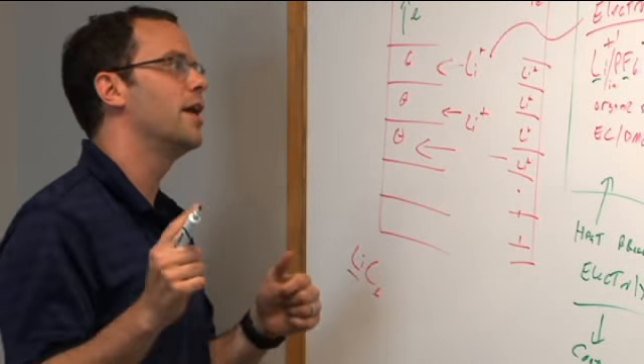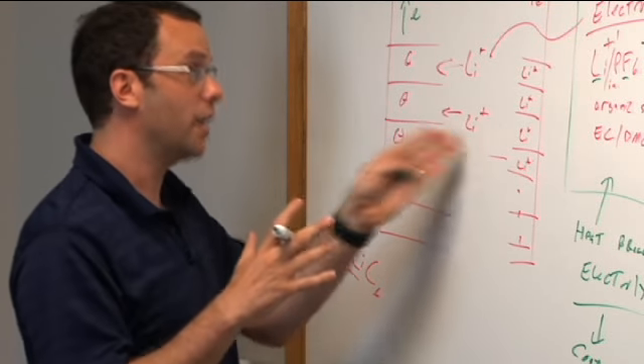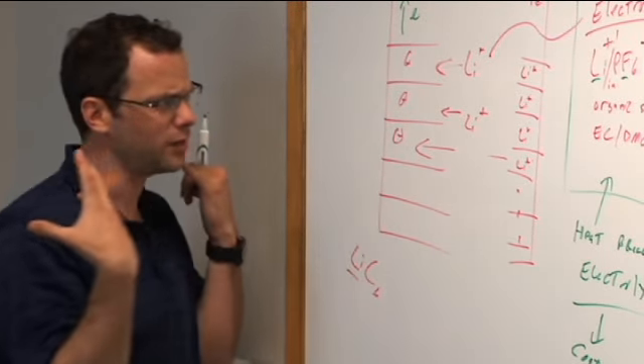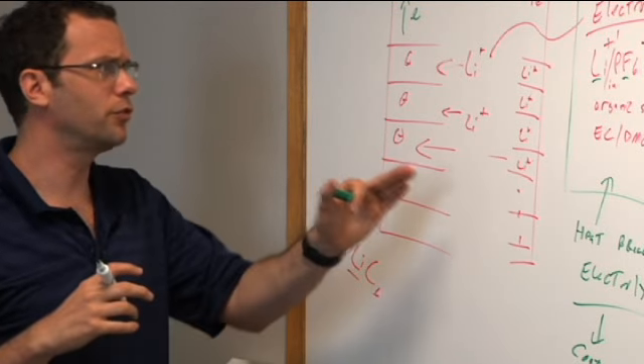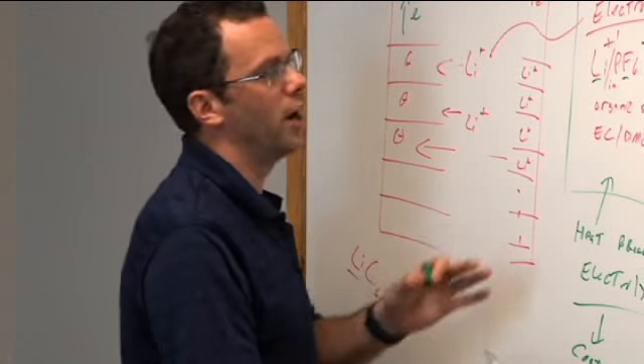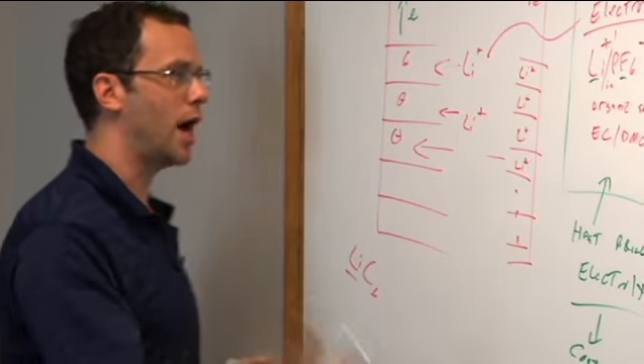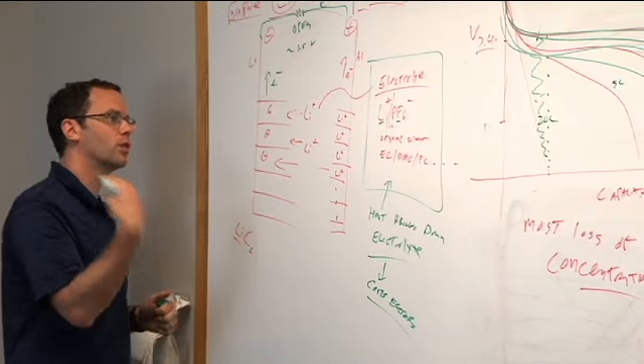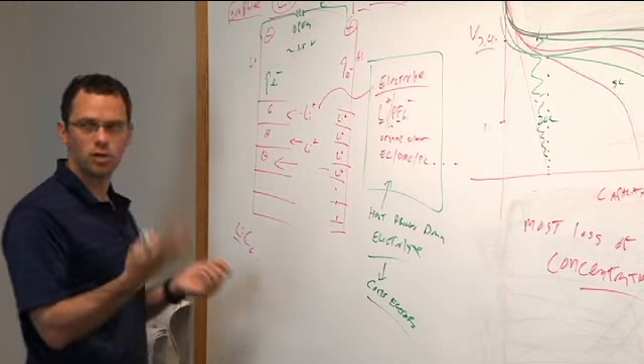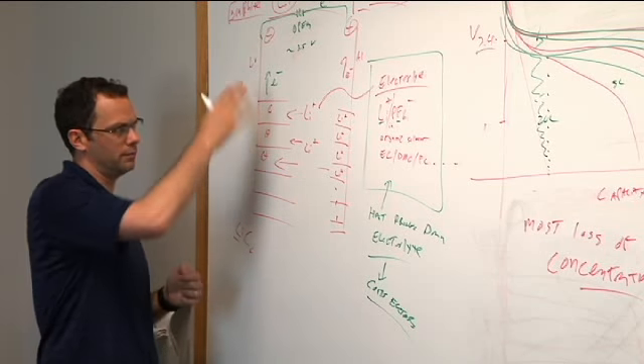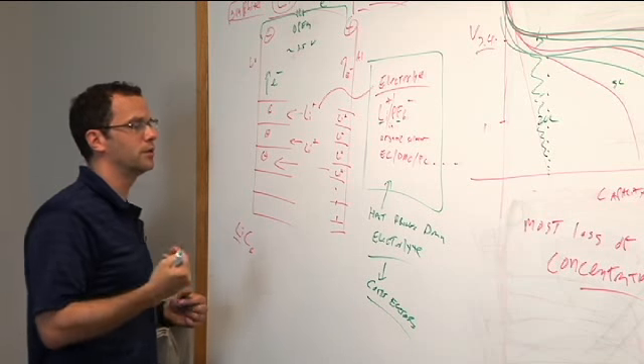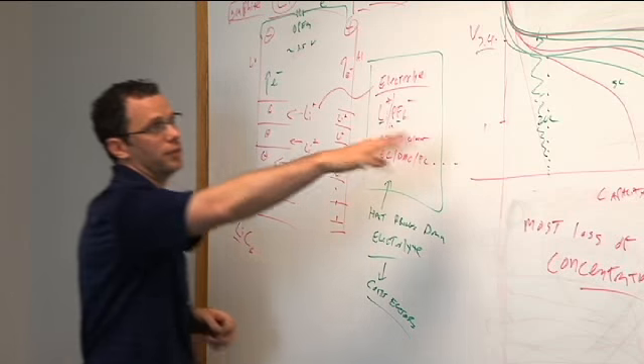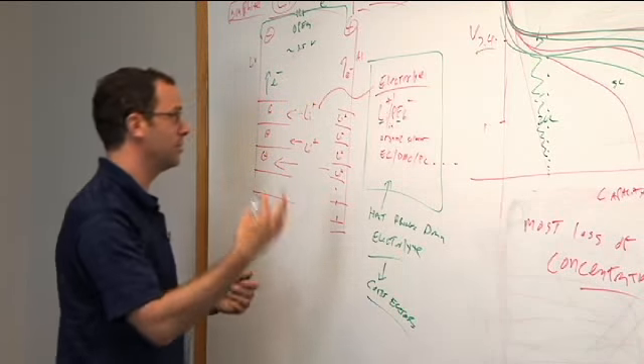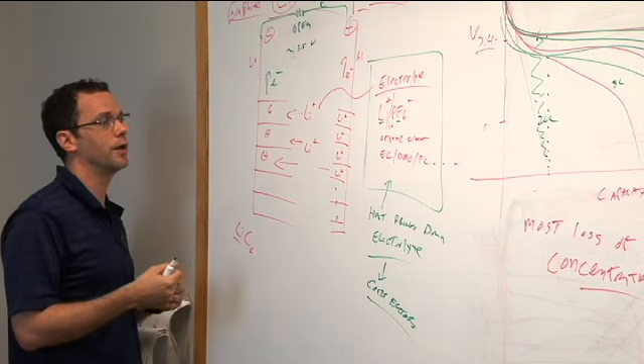But it's an insulating barrier that prohibits motion of lithium in and out of the system, and it limits electronic conductivity. And it also occupies lithium that we were counting on using for charge storage, and now occupies it in this inert layer, and that's our capacity loss too, right? So as we cycle these batteries, this degradation is happening all the time, but it's very, very slow for low temperature, low rate systems. As we go at higher temperatures, higher rates, this degradation happens faster, and we will commonly see a more rapid loss of functional lithium, loss in capacity, as well as a faster buildup of lithium containing inert layers on the anode in particular, and that corresponds with higher resistivity and even more of this diffusion limited problem, because now we have to force our lithium through this layer that's coating the electrode materials as well. Okay, so that's the enemy.